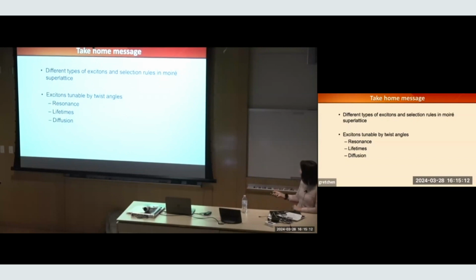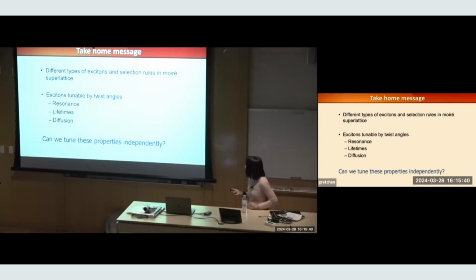So the problem is all of these properties change simultaneously. If I want an array of quantum emitters, I actually don't want a long lifetime. When you have a long lifetime, there are non-radiative decay processes that compete with the radiative decay process. I actually don't want them to change simultaneously. So this has always bothered me. I want to tune these properties independently. Can I do that? The twisted TMD is wonderful, but also has its own limitations. Too many things are changing simultaneously when I twist the angle between the two layers.